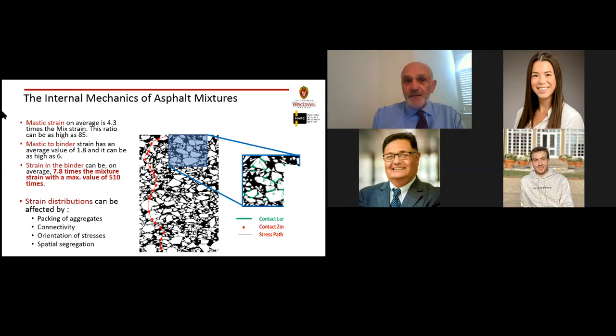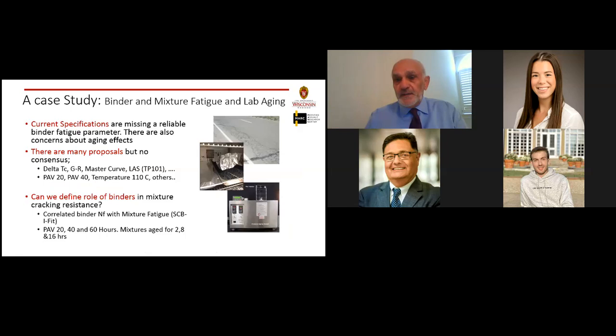We have to recognize that the bulk strain on the mix itself is not what the binder actually exhibits inside it. In fact, one of the studies by Professor Eyad Masad and others clearly indicated that the straining of the binder compared to the bulk mixture behavior is anywhere between 8 and 500 times the bulk strain of the mixtures. Therefore, there is also a recognition that this very complex composite can have different domains geometrically, and these different geometries can result in a variety of strains. And therefore, testing at only small strains would be very difficult. So I promise I'm going to talk about the study.